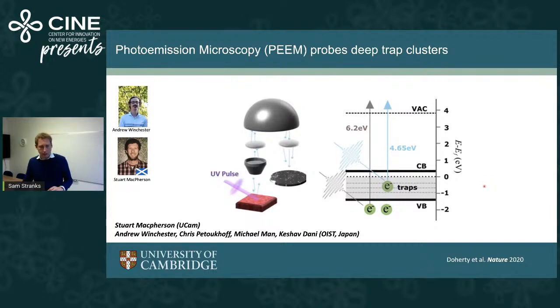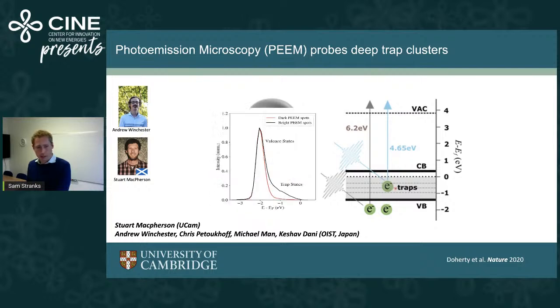I'll start by talking about this photoemission microscopy. This is some work we're doing with Keshav Dani's group in Okinawa, in Japan. Here, we shine a UV probe on these samples, liberating electrons that are bound in these semiconductors. These are photoemitted from the sample. Because we can energy resolve these electrons, we can say how deeply they're bound in the semiconductor. They might be in the valence band of the semiconductor, or they might be sitting in subgap trap states, so we can identify these. And because it's in a microscope, we can also spatially resolve where these electrons are coming from. This is an example of some photoemission spectra. This is the valence band edge here.